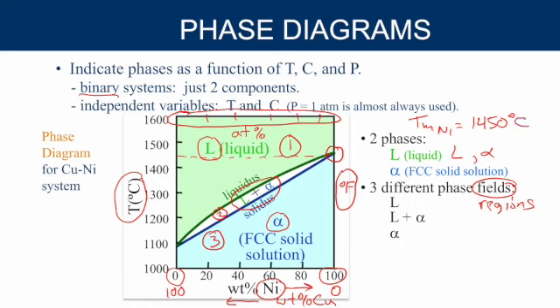What about pure copper? Well, if we have 100% nickel, we have no copper. But if we have no nickel, we have 100% copper. So we do it from the other side of the x-axis. And we get right about, looks like about 1090. So the melting point of copper is about 1090 degrees C. So what's going on in between?